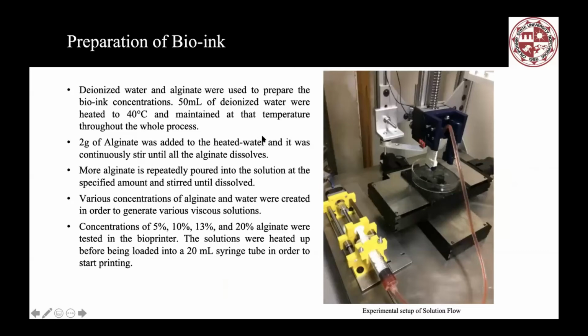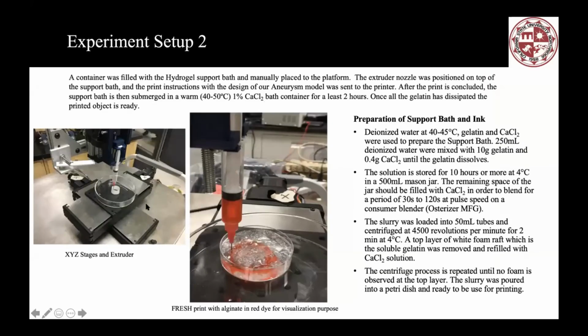So here's the preparation of our bio ink. This bio ink is typically based on dissolved sodium alginate, and we prepare different concentrations and check the viscosities. And here we use two different methods. This is the XYZ stage we developed for our 3D bioprinter. And this is the mold method we use. Here is the fresh print of the alginate with red dye for visualization purposes.